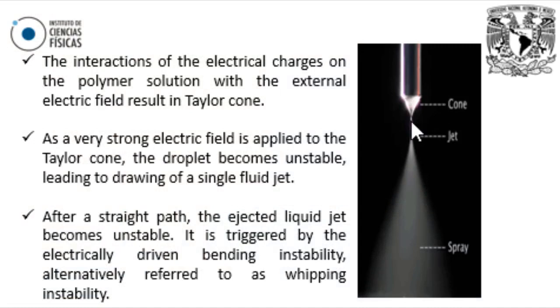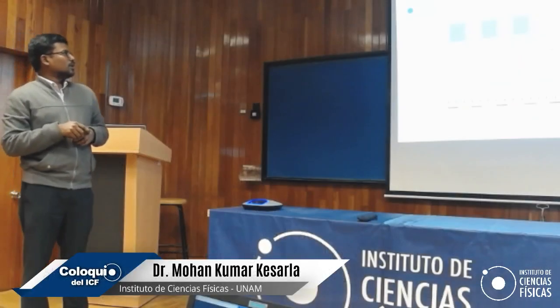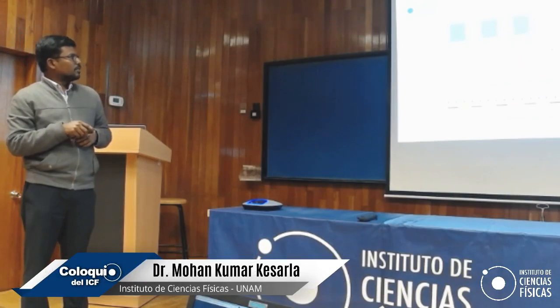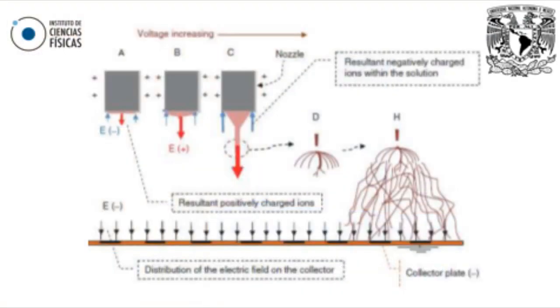After increasing the electrical field, the Taylor cone droplet becomes unstable, leading to a single fluid jet. This is the jet, and then it is triggered by the electrically driven bending instability, where the fiber splits into nanofibers. It will deposit on a current collector. So this is what happens: we charge the polymer, it forms a Taylor cone, and if you keep on increasing the voltage, it will form the nanofibers.